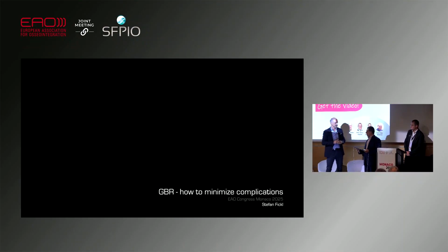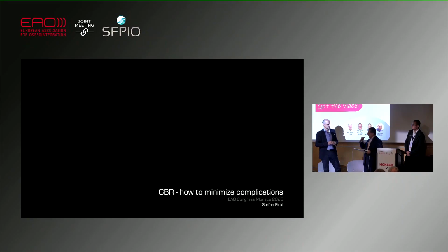No, that's a pivotal difference. It's very important. It's critical because due to this cross-link formulation, the material stays in the wound. Of course, I didn't have the time to elaborate on this. But for example, when I'm doing my surgical procedures, for example, the tunneling approach, I know that I can increase the stability of the flap, the stability of the blood clot significantly more because the material stays there for a couple of weeks, maybe up to 4 to 6 weeks.